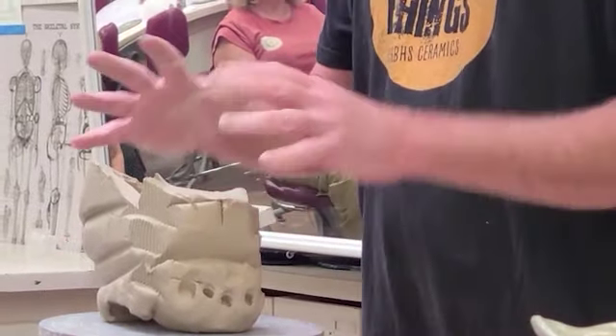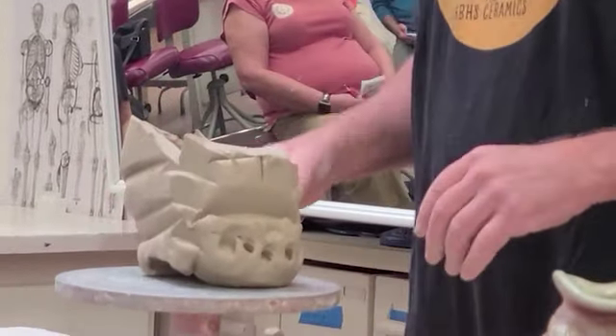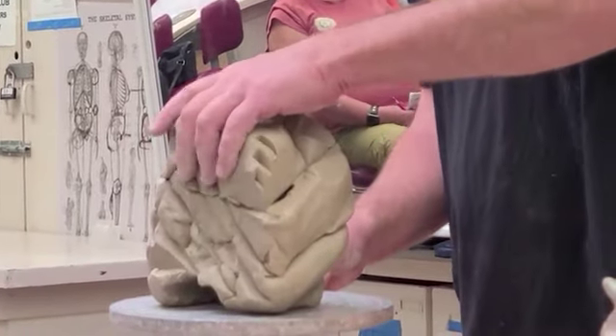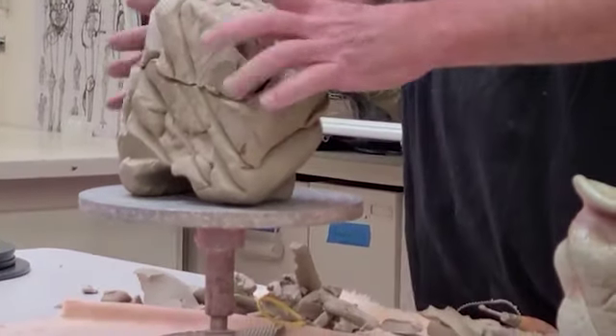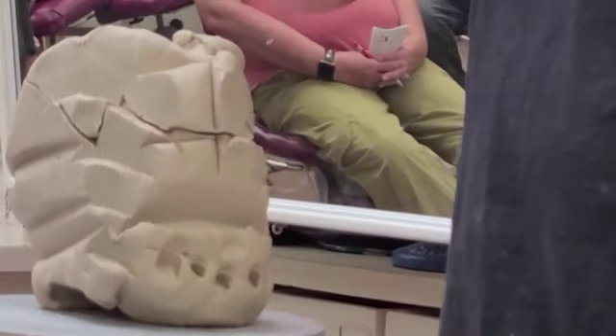So instead of boring you just watching me carve this thing out, does that get you the general idea of how you can make one of these things? You go down and really get in there and test your thickness, and then that one, and then you would fire them together in the bisque kiln. Fire it just like that in the bisque. And then if you're going to glaze the inside, glaze it, except leave all the edge unglazed. I would glaze fire them together, because if you high fired them separately, they would warp and then wouldn't go back together.